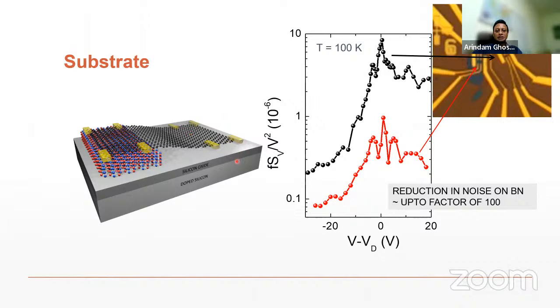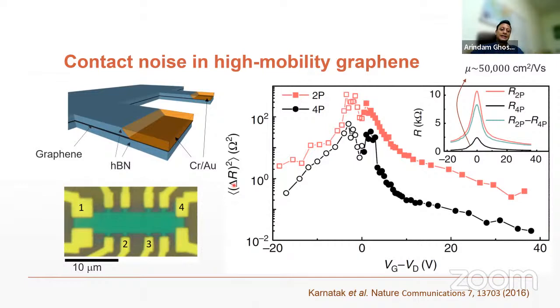So clearly, the noise from the substrate constitutes a substantial part of the noise that you measure in graphene devices. Then we realized that, oh, hang on, there is more to that. And this is something which Paritosh did, and he measured the noise in a van der Waals heterostructure of graphene, in which the graphene was encapsulated in between two layers of boron nitride, like this, and then he put a Hall bar measurement. That means the current, when it goes through graphene in this direction, the voltage leads do not overlap with the path of current.